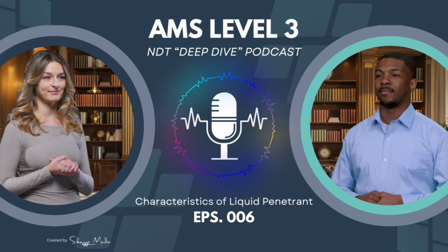So that brings us to the better alternative, hydrophilic emulsifiers. Yes, these were a real game changer. Hydro, meaning water-loving. These are different. They're typically detergents or dispersants dissolved in water. So how do they work differently? Instead of diffusing into the penetrant, they work by preferentially wetting the metal surface underneath the penetrant layer. They sort of gently lift or peel the excess penetrant off the surface. Like getting underneath it. Kind of, yeah. And they break it up into tiny droplets that get dispersed in the water